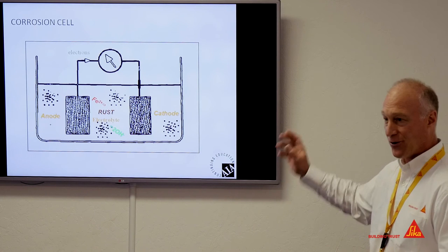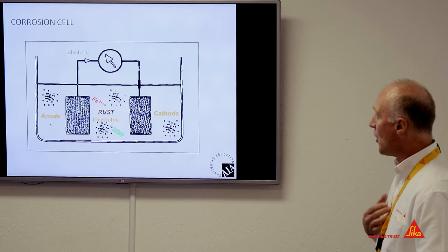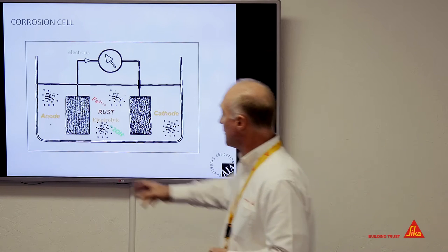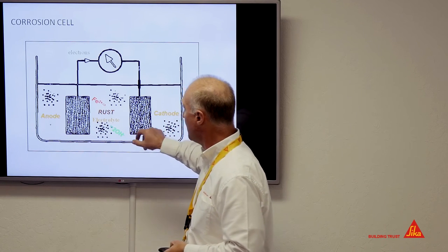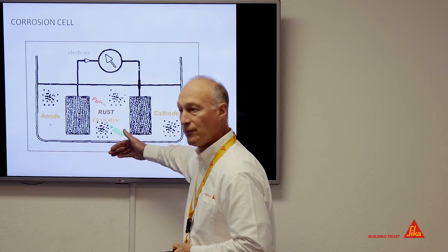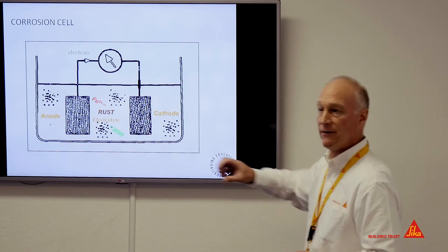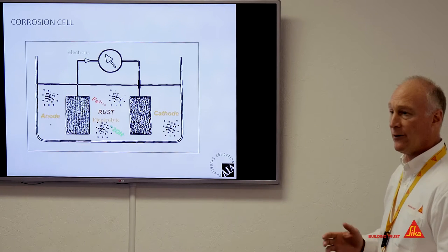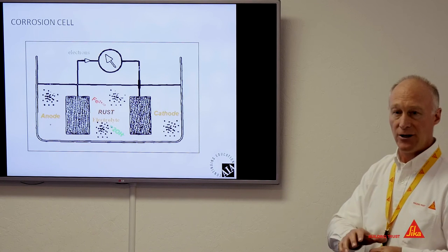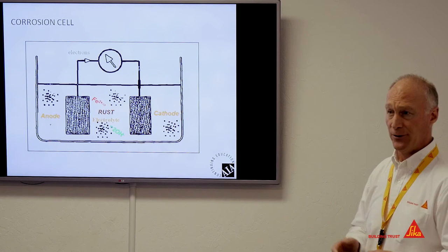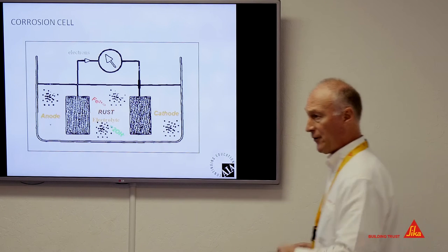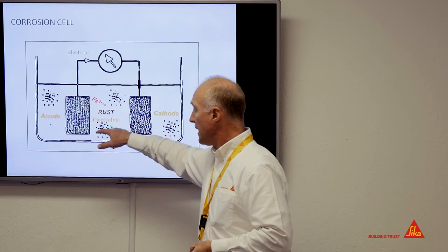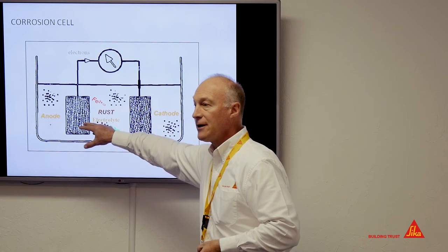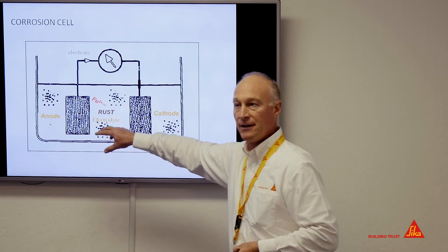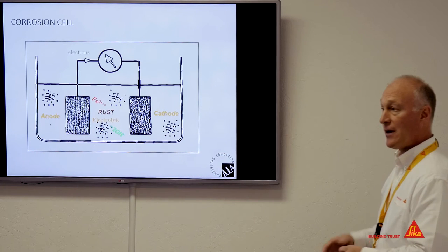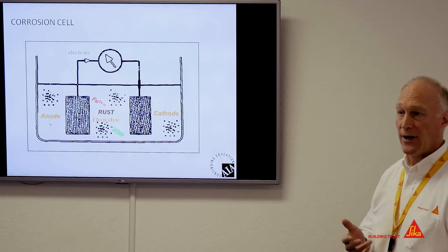But you need the cathode in order to support that reaction. So our approach is to try to eliminate either the anode or the cathode, or bring the moisture level down and limit the availability of oxygen or water. If we can do any one of those four things or a combination of them, we'll have the same effect on corrosion. What Graham's going to talk about with cathodic protection is how you eliminate the steel from being the anode, because that's where the corrosion is taking place. You do that in an artificial manner through cathodic protection.